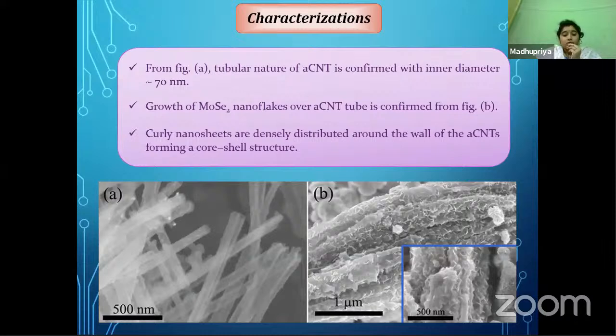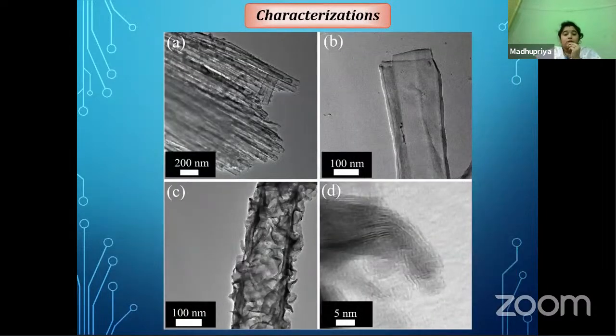These are some morphological FESEM images. Figure A corresponds to the bare carbon nanotubes of inner diameter around 70 to 90 nanometer, and figure B represents the decoration of MoSe2 nanoflakes over the carbon nanotubes. These are some TEM images, and from them we found the thickness of the nanoflakes is in the order of 4 to 5 nanometer.